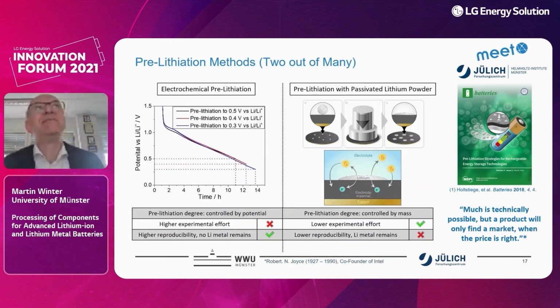We investigated this by comparing two pre-lithiation methods, 2 out of many. We have also done others, but I want to show just these two here. One is the well-known electrochemical pre-lithiation, where you control the pre-lithiation degree by potential. Here, for example, pre-lithiation to 0.5 down to 0.3 volt against the lithium metal counter electrode. Or the pre-lithiation degree is controlled by the mass of the lithium that has been inserted in the electrode mix. Here we take lithium powder because that is much easier to dose than lithium metal foil.